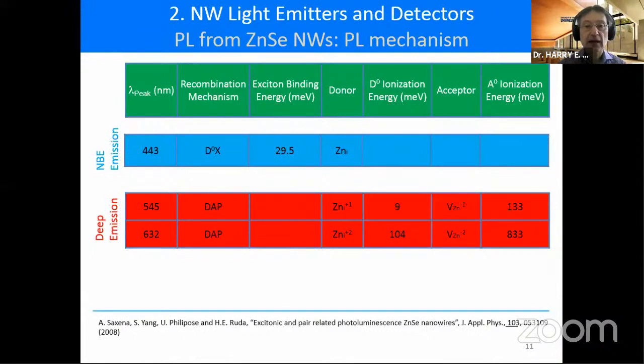Rather than go through the complete analysis with you, because we don't really have time, I just wanted to draw some attention to what's going on in these systems. The near band edge emission, as I said, is donor bound exciton recombination, and it involves the zinc interstitial as the principal donor. The deep level emission, the red band, is also due to the same donors, the zinc interstitial donors, but the acceptors are now zinc vacancies, singly and doubly ionized vacancies. So you have a Frenkel equilibrium that's controlling the deep level emission, the red emission, whereas you have donor bound exciton emission just involving the zinc interstitials for the near band edge.